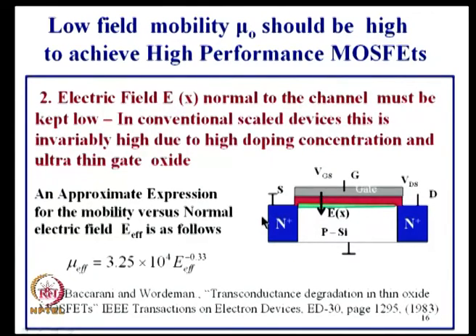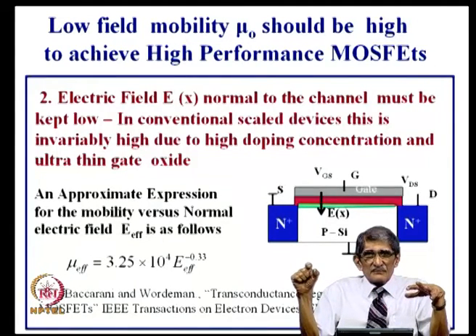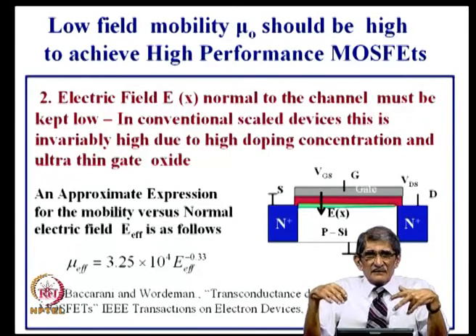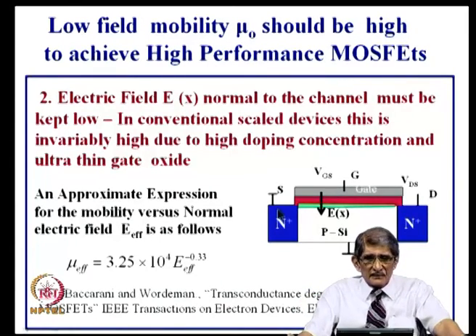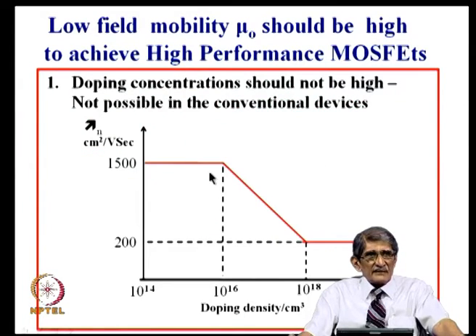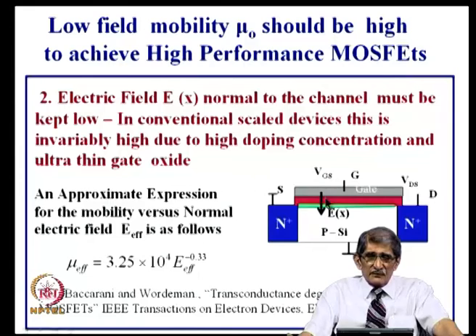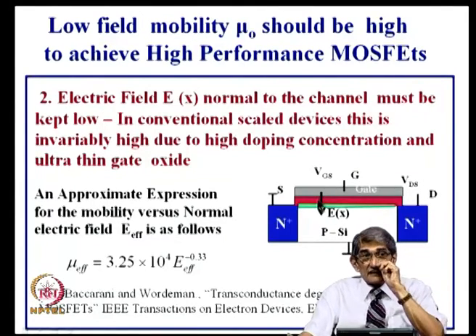So, what is the way to handle this? You can't help reducing the oxide thickness, because you want to keep the capacitance large. What you can do is reduce the doping concentration here. If you reduce the doping concentration in the channel, two things happen. One, the ionized impurity scattering gets reduced, so mobility reduction does not happen. You can go to mobilities as high as 1500 in silicon. If you use some other material, you can have mobilities decided by the mobility of electrons in that material. Okay? And also, if you reduce the doping concentration here, the depletion layer charge gets reduced.